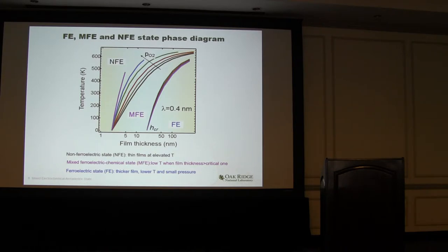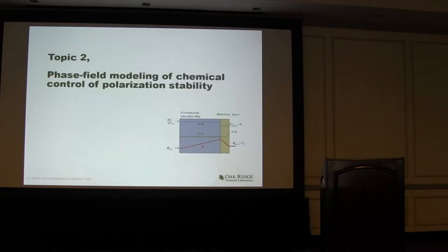We also see that when the oxygen partial pressure increases, the boundary separating the non-ferroelectric and mixed ferroelectric state has a dependence on oxygen partial pressure. The boundary between the mixed ferroelectric and ferroelectric state has less dependence on oxygen partial pressure. Using the thermodynamic analysis, we quantify the existence of this mixed ferroelectric state.